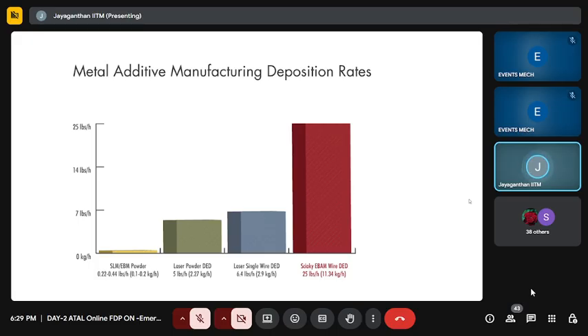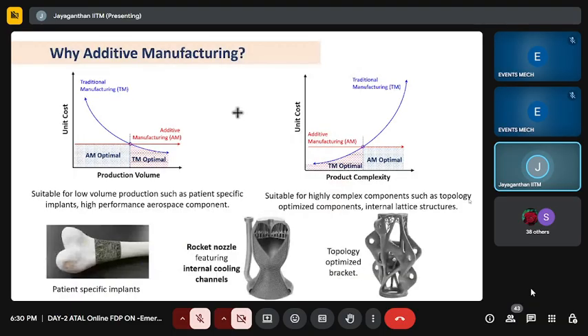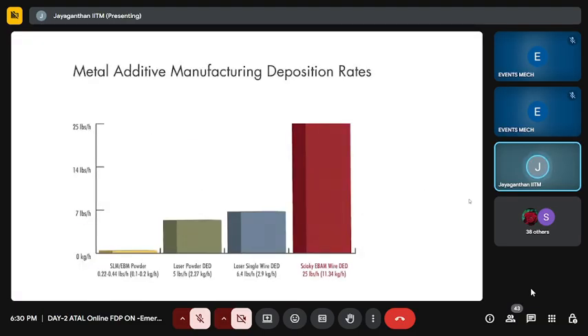That is utilized only for making very, very complicated sizes and shapes, for example, in the previous slide I showed the topology optimized bracket actually. Very complex shaped geometry. Looking at the internal size feature, if it is a few micron or submicron thick, you should always go for extreme left actually. For weld repair, obviously you can choose the single wire DED at 2.9 kg per hour deposition rate, or you can see at the extreme right, electron beam additive manufacturing. There also we have wire-based direct energy deposition. You can see 11.34 kg per hour. There you cannot get very minute features like micron or submicron. That's where we go for using extreme right actually.